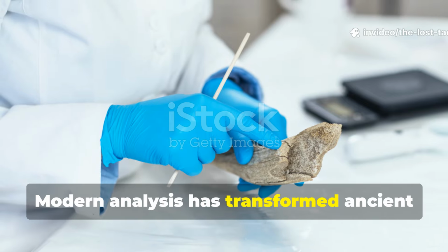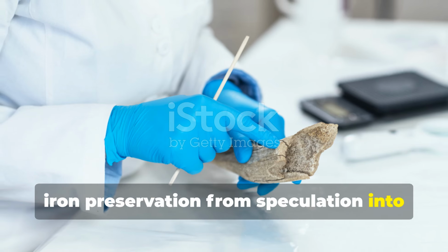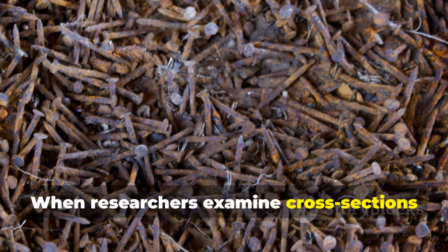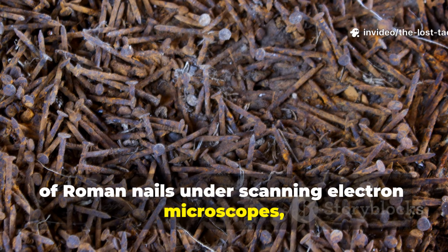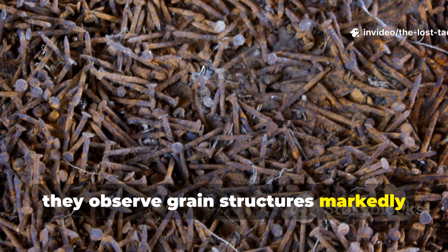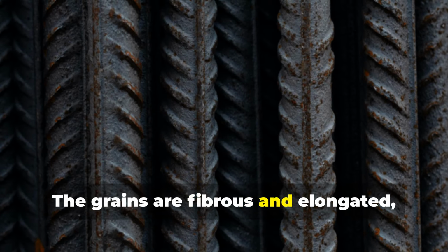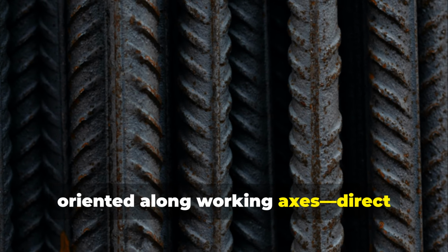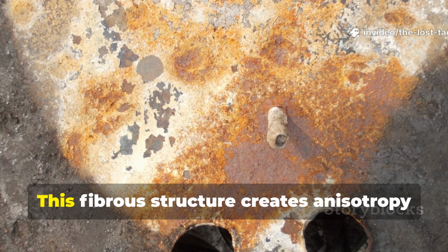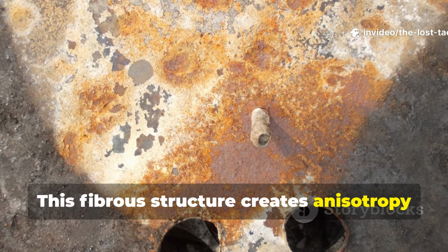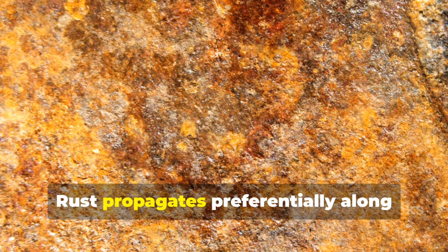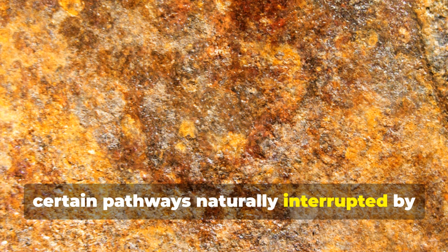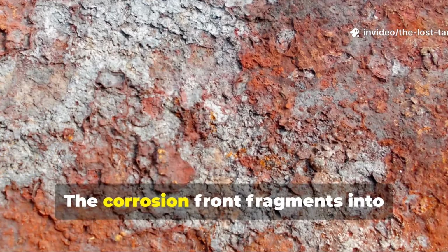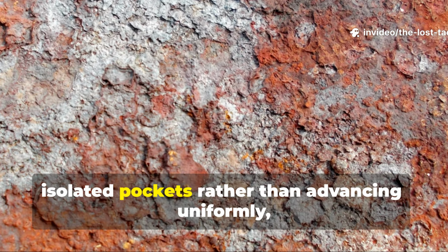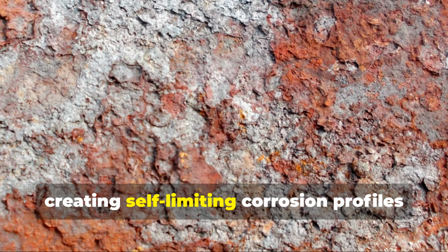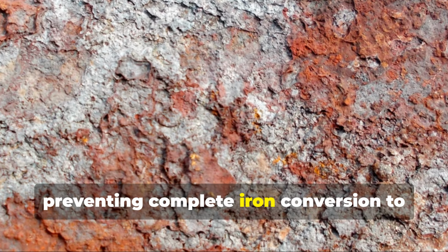Modern analysis has transformed ancient iron preservation from speculation into measurable fact. When researchers examine cross-sections of Roman nails under scanning electron microscopes, they observe grain structures markedly different from modern iron. The grains are fibrous and elongated, oriented along working axes, direct results of bloomery forging processes. This fibrous structure creates anisotropy in corrosion. Rust propagates preferentially along certain pathways naturally interrupted by slag inclusion distribution. The corrosion front fragments into isolated pockets rather than advancing uniformly, creating self-limiting corrosion profiles, preventing complete iron conversion to iron oxide.